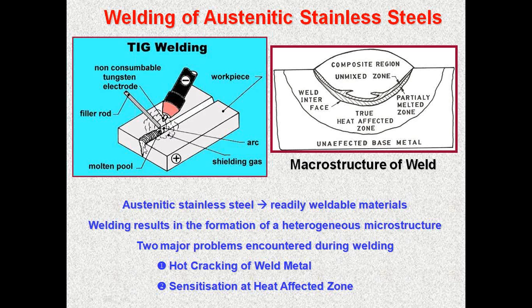the melting and then cooling under a condition which is not controlled will lead to heterogeneities in the structure. There will be a heat affected zone due to the thermal cycling by multi-pass welding. Also the weld structure will be very composite in nature. There are two issues with respect to austenitic stainless steel welding. One is hot cracking due to the impurity elements that are present, and the other is sensitization in the heat affected zone, which we have already discussed. So one has to take a lot of care to avoid these two issues: hot cracking by controlling the heat input, or by controlling the chemical composition of the base as well as the filler wire or the welding electrode, and sensitization also by controlling the other parameters.